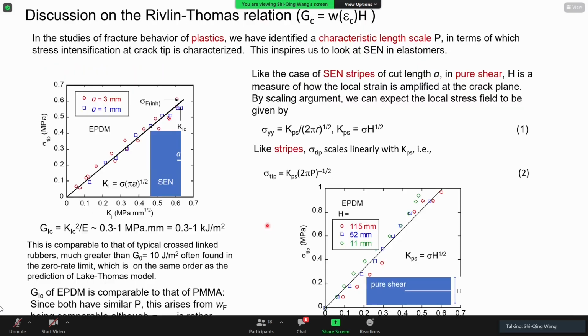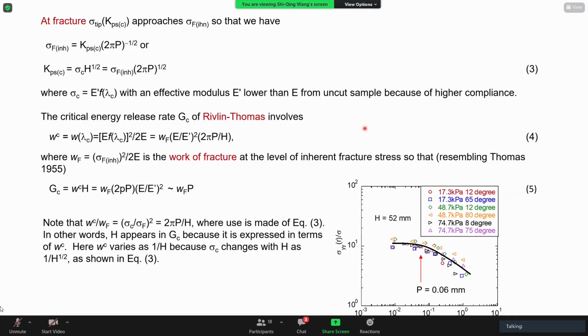In any case, we were interested in contrasting a single edge notch study involving different diameters, different cut lengths, and pure shear. Look at this pure shear problem. The tip stress converges to the same master curve if you insist that your K for pure shear involves the far load stress and the height of your sample. So this allows me to reach the demonstration of where the Rivlin-Thomas expression comes from. Without going into any details, the plastics argument for single edge notch or pure shear eventually involves a similar thing.